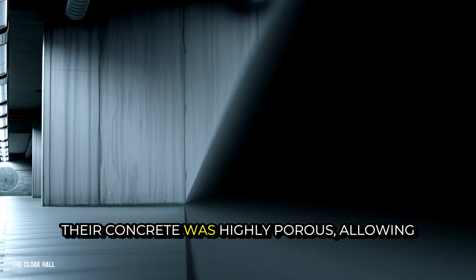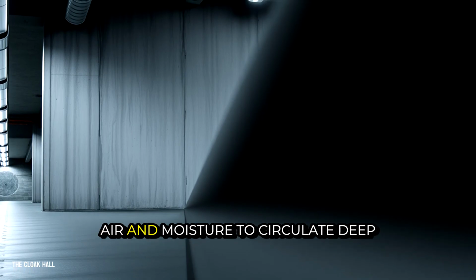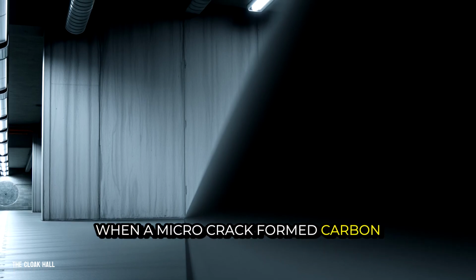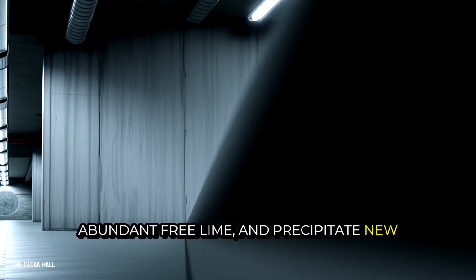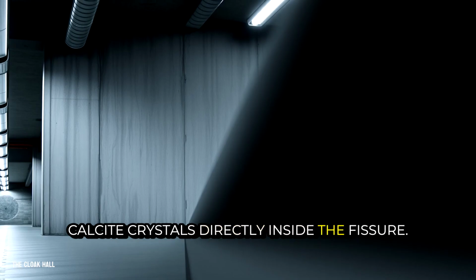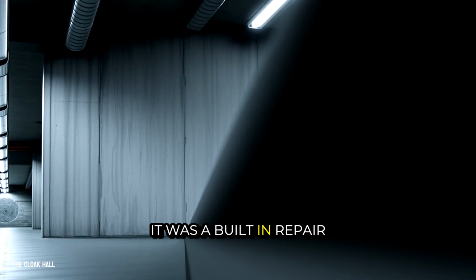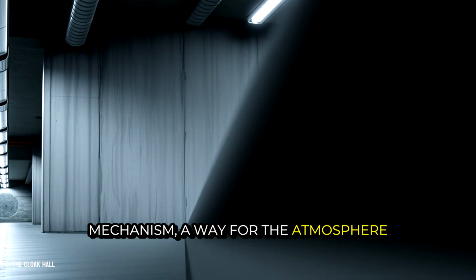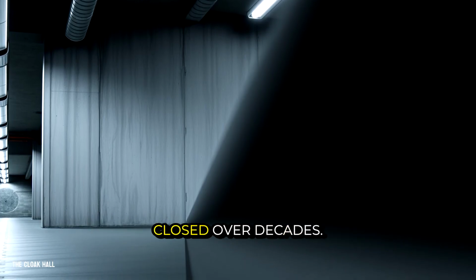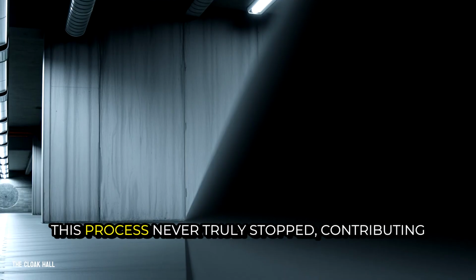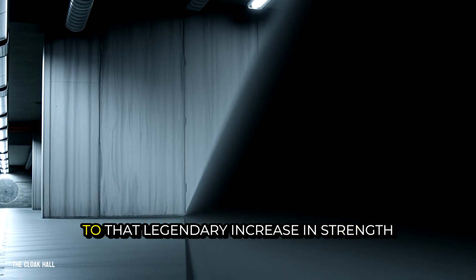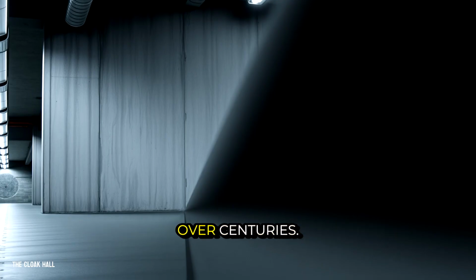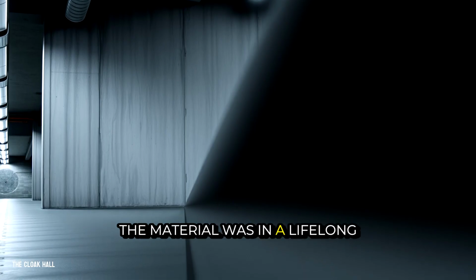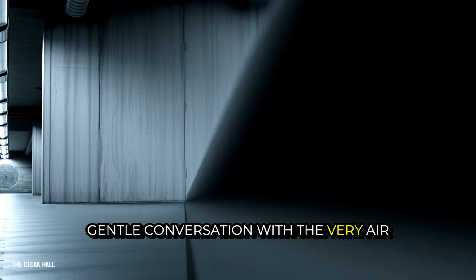Their concrete was highly porous, allowing air and moisture to circulate deep within its matrix. When a microcrack formed, carbon dioxide could diffuse in, meet the abundant free lime, and precipitate new calcite crystals directly inside the fissure. It was a built-in repair mechanism, a way for the atmosphere itself to gently stitch small wounds closed over decades. This process never truly stopped, contributing to that legendary increase in strength over centuries. The material was in a lifelong, gentle conversation with the very air around it.